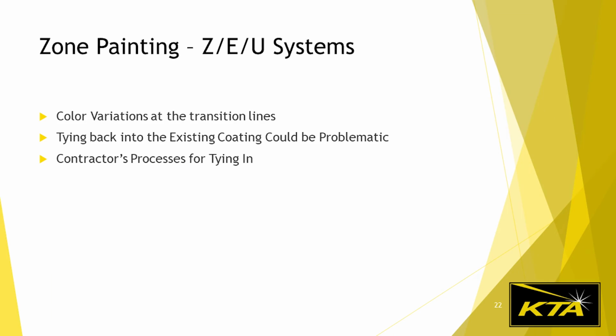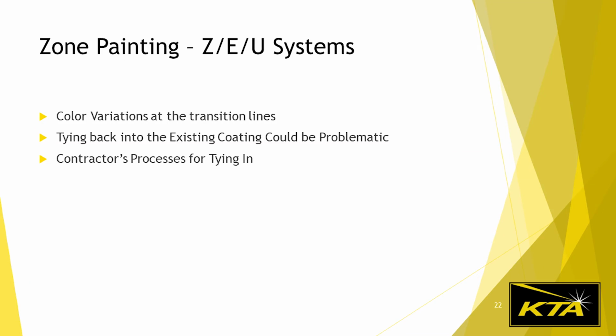A couple of things to consider with zone painting. It's not going to be a feasible option if aesthetics are really important to you. There's going to be color variations in the spans. You can try to match the faded color, but there will be a clear difference. The transition areas of new paint to existing paint could become a problem if not done correctly. Each coat should be tied back into the existing coat, so new zinc primer tied back into the old zinc primer and intermediate as well. A well-written spec will require feathering to tie them back in. These areas should also be tested with a dull putty knife to make sure it's tightly adhered.